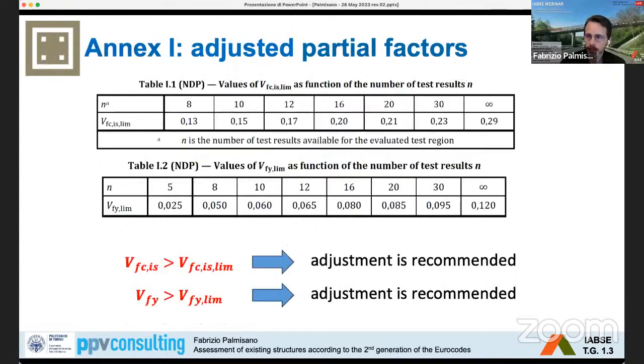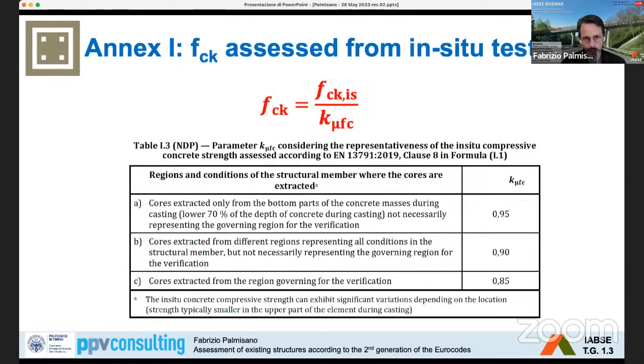As I said, in Annex A, there is the permission to adjust the partial factor. This is a possibility. However, this is slightly different in Annex I when dealing with existing structures. Because if the coefficient of variation of concrete is higher than a given limit value, or the coefficient of variation of steel reinforcement is greater than a limit value given in this table, depending on the number of test results made on the existing structure, the adjustment is not only permitted, but is recommended. Because if in this case we use the same partial factor as given for new structures, so the fixed partial factor, we are not on the safe side anymore. So it is recommended to adjust the partial factor.